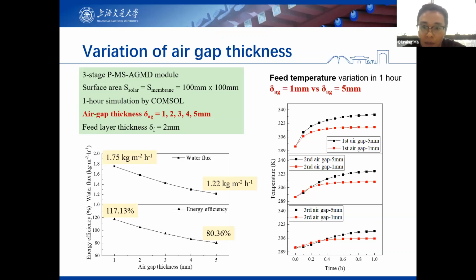And additionally, we can see that because all the temperatures in each stage are lower with thinner air gap thickness, in that case, the heat loss to the ambient seawater or the air can be lower because the temperature is lower. That also contributed to the higher performance.